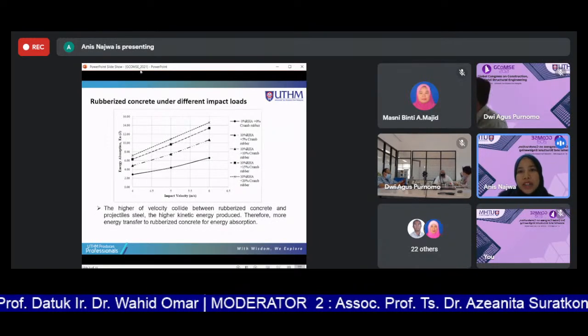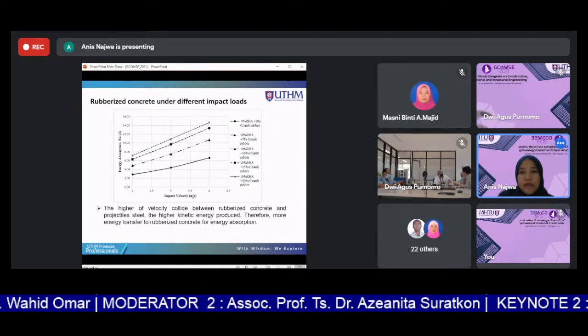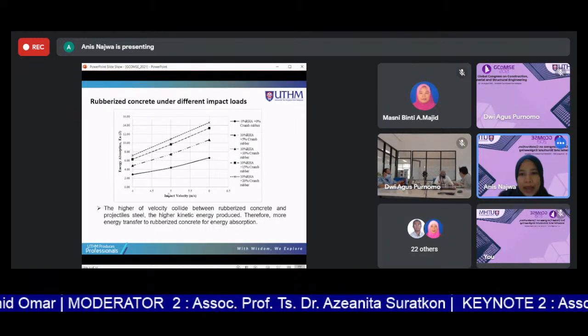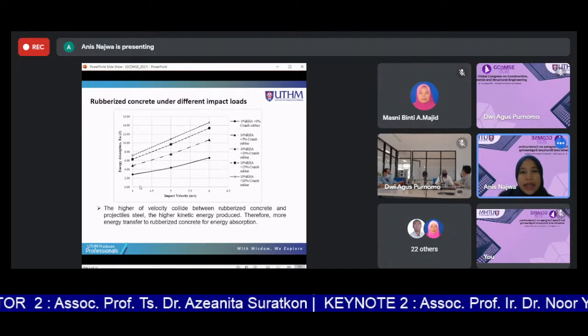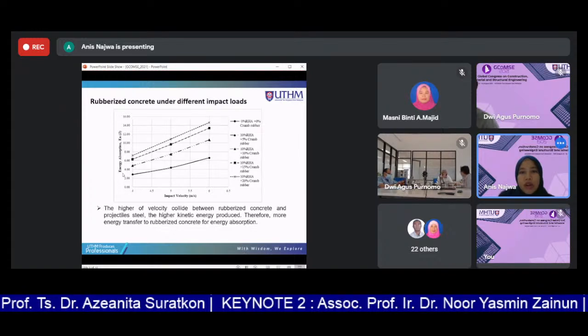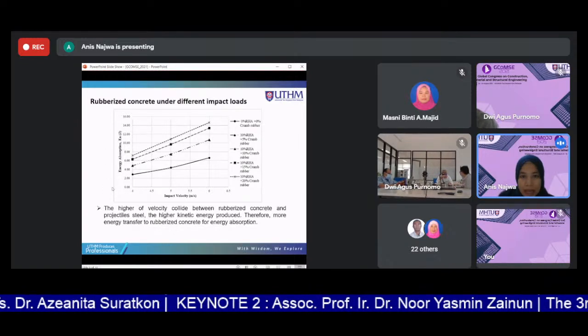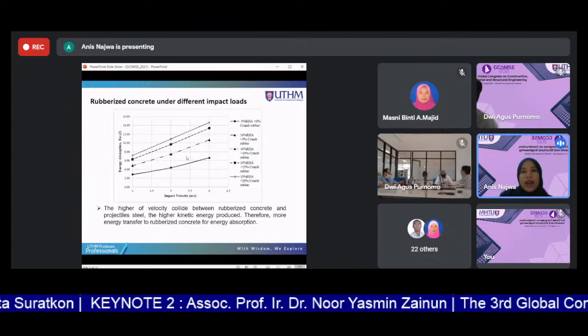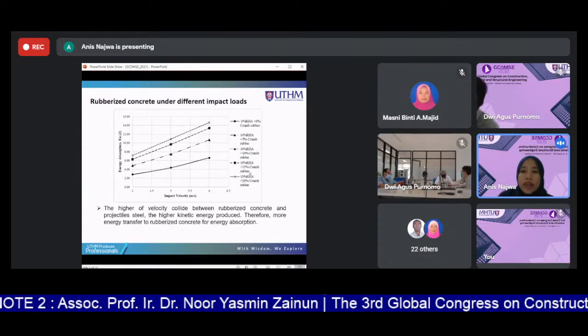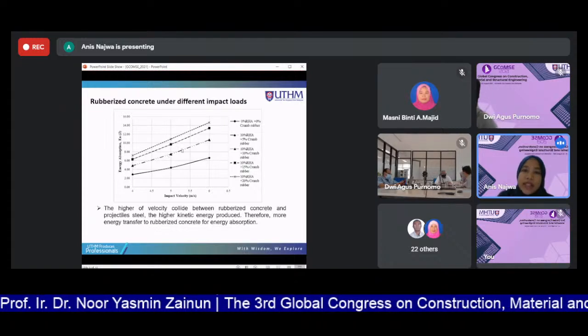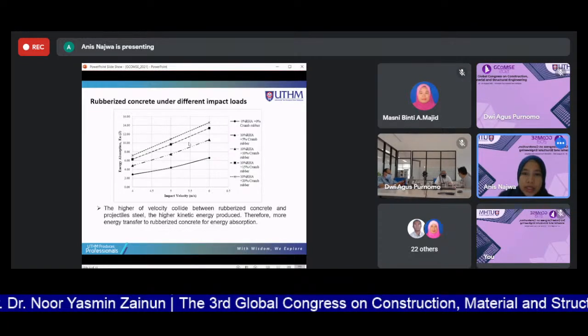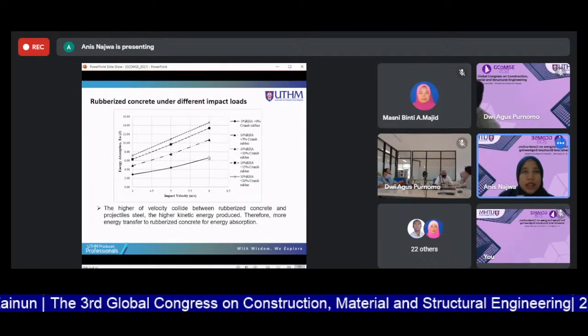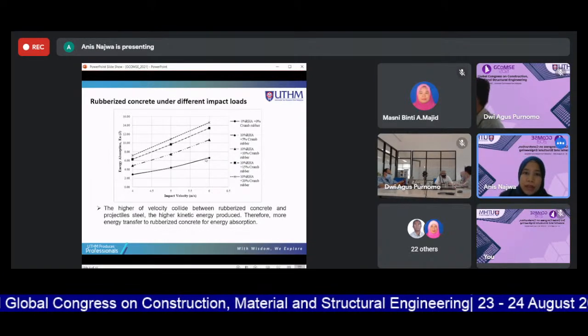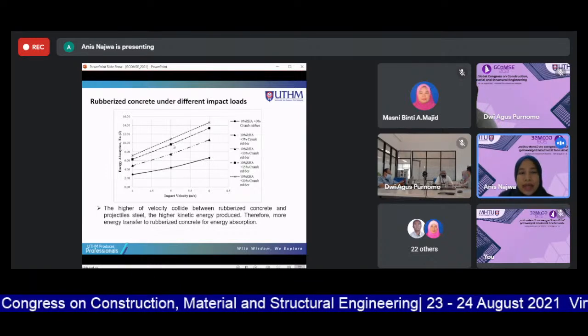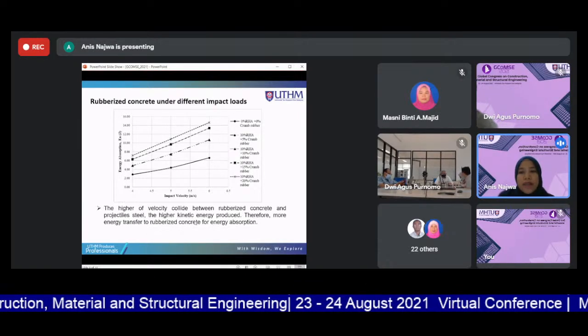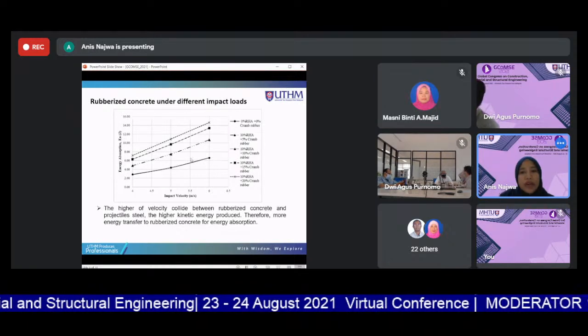So for the rubberized concrete under different impacts, here are the different velocities that have been used and also the energy absorptions. The higher the velocity, the higher the energy absorption result. And what is most interesting here, the higher the percentage of rubber replaced, the higher the energy absorption. This is quite interesting because it shows that rubber is good in terms of energy absorption, so it can be used as a concrete barrier. Therefore, more energy is transferred to the rubberized concrete for the energy absorption.